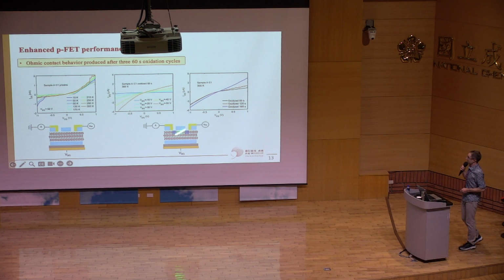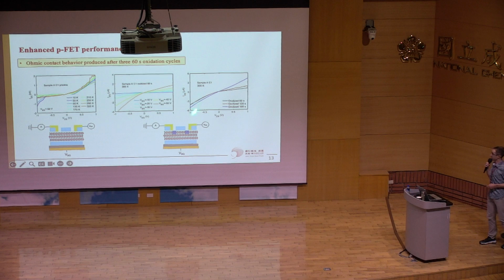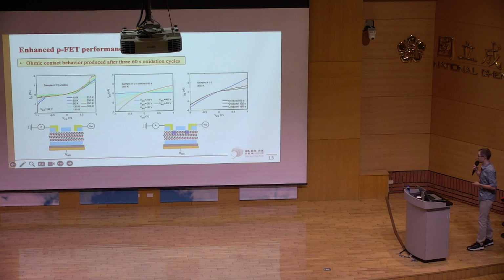If we then measure the sample after the oxidation process, this is at 300 Kelvin, so basically room temperature, sweeping the gate for different gate voltages. At the largest bias here, we can see that it's still not symmetric, but the current has increased significantly. Here we're looking at nanoamps. After oxidation, we're looking at microamps. What we'd like to see is a nice straight line, which is what we know as ohmic contact behavior.